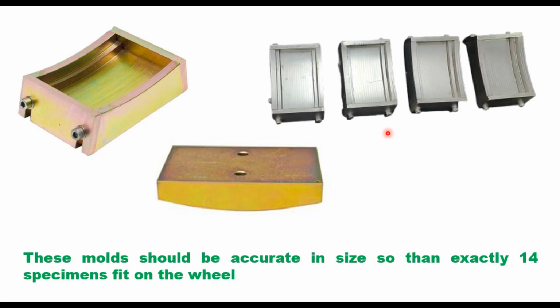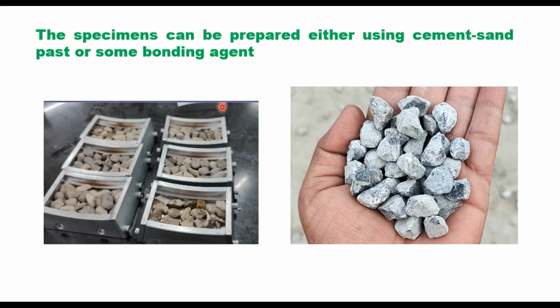Here are metal molds, and these metal molds are used to prepare the specimen. These molds should be accurate in size so that exactly 14 specimens fit on the wheel. That is the shape of the mold, and that is the cover of the molds to give the shape to the final specimen. A specimen can be prepared either using cement sand paste, or using some bonding agent.